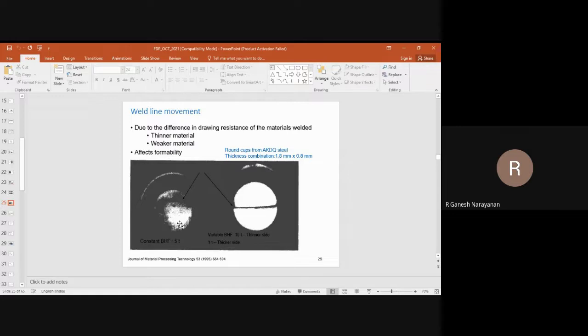Why does the weld line move? The weld line moves because there is a different drawing resistance to the materials. One material will have one drawing resistance when compared to the other. So one is going to pull the other material, so the weld line automatically moves. But we don't want that, right? So you want the weld to be at one particular location only. So how to avoid this weld line movement? First one is giving different blank holding force. Okay. So in this case, a constant blank holding force is used, that is 5 tons. But in this case, if you see, they have used a variable blank holding force. That means on the thinner side, they use 10 tons, on the thicker side, they use 1 ton only. So you resist the movement of the thinner material so that your weld zone is at the center. So one way to avoid weld line movement is to provide different blank holding force.